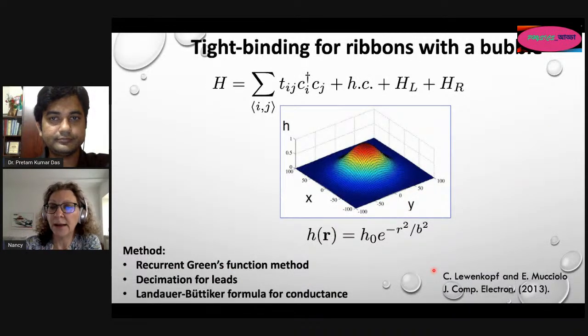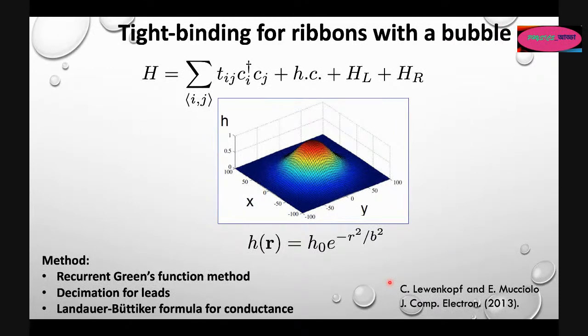Okay, so let me now go to applications, and I will go fast here. So the first application that we studied was to say, well, let's try to see if we can connect the deformations that we're observing in the experiments done by STM tips with a model that mimics or tries to represent the presence of a bubble in a graphene membrane. So we said, let's start doing a tight-binding Hamiltonian in real space, write a code to represent this Hamiltonian and solve it numerically. And let's represent the deformation that is produced when it is measured, or for the graphene sitting on top of an impurity or a compound when it's deposited on a substrate, by a Gaussian shape, okay?